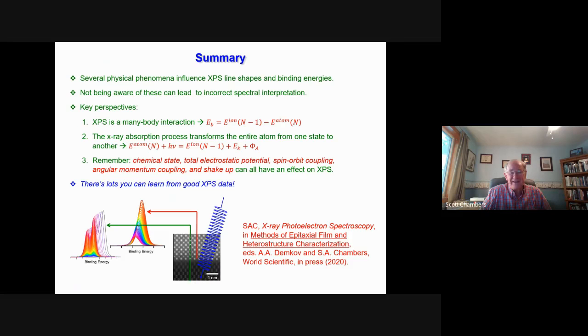Yeah, it really is crazy. Oxides are complicated, really are complicated. And these effects can kick in, and the relative weight of these different effects, mainly charge distribution, angular momentum coupling, and shakeup. Those three can actually influence one another, and they can couple together to give you final states that are not what you'd expect at all. And without first principles calculations, sometimes it's very difficult to know what these things mean. And that frustrates people because they want to just look at the spectrum and say, oh, this means this. And you just can't do that accurately, unfortunately, for some of these, mainly for transition metal containing materials.